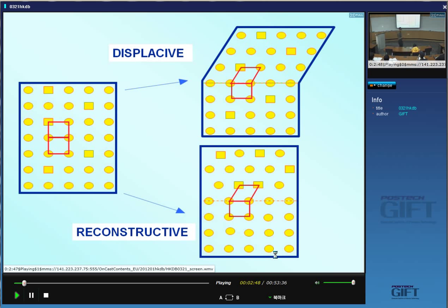And that is why we get a shape memory effect with displacive transformations, because you are just recreating the arrangement of atoms without losing neighbors. Furthermore, if you look at this, the chemical composition of this region is exactly identical to that region, the corresponding region in the parent phase. But the most important thing to notice here is that given that we changed the pattern in which the atoms are arranged, the overall shape has also changed. And that is the macroscopic shape deformation, which we call an invariant plane strain. Right? It leaves this plane undistorted and unrotated on a macroscopic scale. But it's also very large, because if this is surrounded by other crystals, then it's going to cause a lot of strain energy. So these are strain energy dominated transformations.